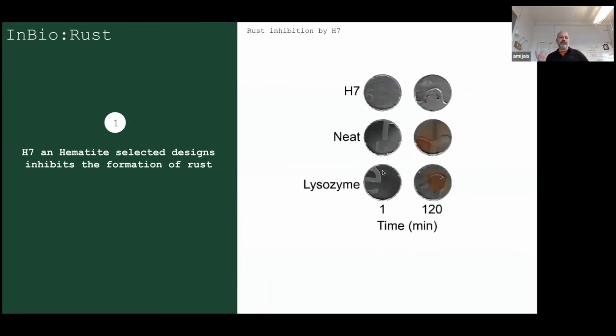Another funny thing is that we found out that if we take H7 and we put it on iron, we saw inhibition of the formation of rust. So you see that if we mix it with lysozyme, after 2 hours, these are buffers, so you have a lot of salt. The reaction happened quite quickly. You get a lot of rust, lysozyme or just buffer. But if we add our protein, we somehow inhibited this. We're not sure about the mechanism here, but perhaps it's to do with the protein binding it and forming small pieces of hematite or something like this.